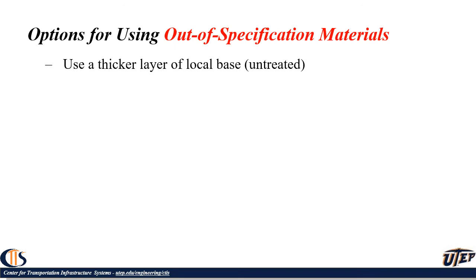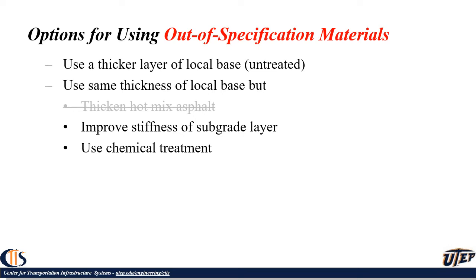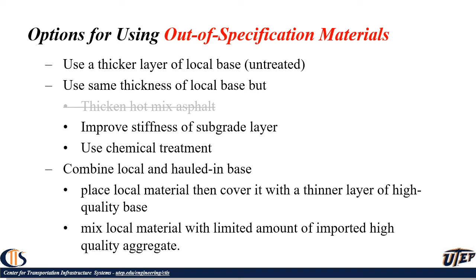The options we used for using out of specification materials are shown below. The first one was using a thicker layer of local base. The second one was to use the same thickness of the local base, but thicken the hot mix asphalt that we eliminated because of the cost. Improve the stiffness of the subgrade or use chemical treatment. And the other group of options were to combine local and haul-in base. One was to place a local material, then cover it with a thinner layer of high quality base, and then the other one was mixing the low quality material with the limited amount of high quality imported material to improve the properties.